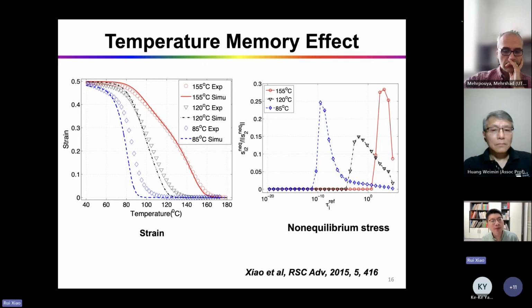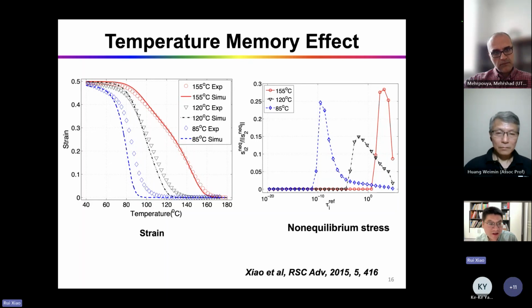What do you learn from them? Why do they have temperature memory effect? So the model can actually tell you something. If you program the SMP at high temperatures, it's actually the relaxation process with large relaxation time that really fixes the temporary shape. If you program at low temperatures, it's actually the relaxation process with smaller relaxation time that really fixes the temporary shape, so you can recover earlier.